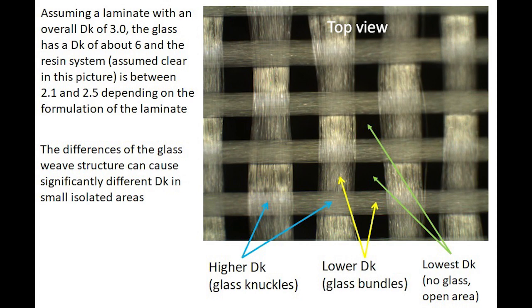So if the overall dielectric constant of the laminate is meant to be 3, which is pretty common with millimeter wave applications, then the resin system must be much less than 6, which is what the glass is. Normally it's down around 2.1 to 2.5 for dielectric constant, depending on the formulation and how much glass is used.